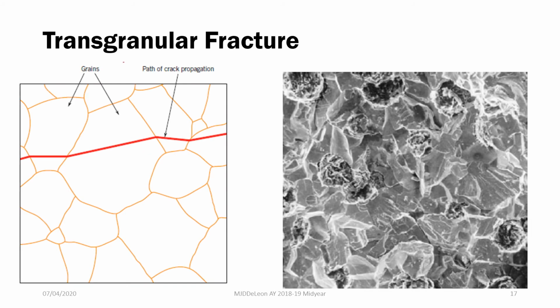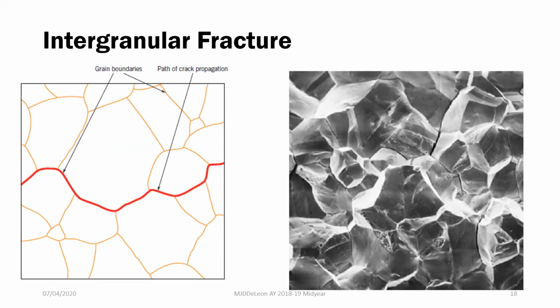So in terms of crack propagation, we have 2 different routes. First is our transgranular fracture in which your crack propagates in the grains. Counterpart to that, you have your intergranular fracture. Pag intergranular fracture naman, your crack propagates on the grain boundaries. So, whether or not transgranular or intergranular yung fracture natin depends on the type of stress applied and whether or not mas stronger yung grain boundaries natin or yung grain surface mo. So, there are a lot of different factors that we consider. So, itong transgranular versus intergranular fracture nyo, ma-learn nyo naman siya in a higher MatE subject.